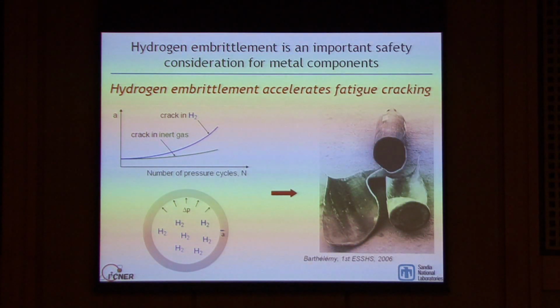To illustrate why hydrogen embrittlement has to be considered from a safety perspective: if we consider a hydrogen containment structure like a pressure vessel or pipeline, these components are invariably subjected to pressure cycling, and this pressure cycling can enable fatigue crack growth. If we think about a cross-section through a cylindrical component like a pressure vessel or pipeline, represented here in the lower left corner, subjected to pressure cycling, particularly in the presence of hydrogen, cracks can start to grow in the walls of these structures.